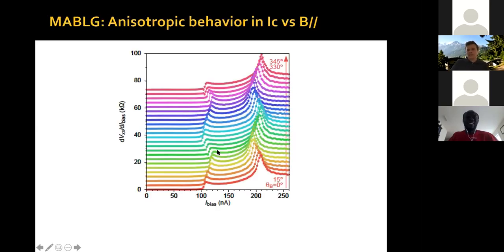Now, this tells us again, I don't want to comment too much about this. This could be due to different nematic domains, etc. But both the critical parallel magnetic field and the behavior of the critical current versus parallel magnetic field tell us that the system, the superconducting state, exhibits an anisotropic response, and in particular, a C2 symmetric response. The system chooses a given direction, okay? Now, that's for the superconducting state.